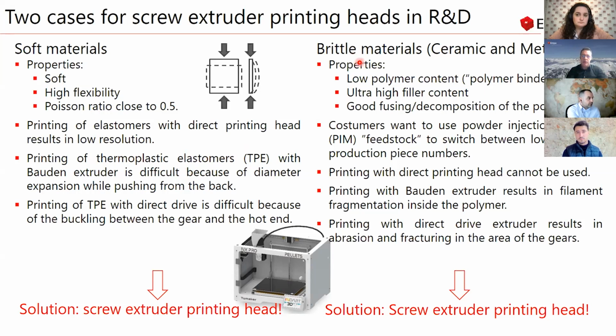On the other hand, let me look at the brittle materials, so ceramic or metal filaments. And here typically we have a low polymer content, we have high filler content logically, because we want to decompose the polymer afterwards, and we will then use a sinter process to consolidate the material and to have a dense ceramic or metal part. Therefore, for the printing part, we need a good fusing of the small polymer amount which we have inside. On the other hand, we need a very good decomposition of the polymer so that we can remove the polymer before we do the sintering process.